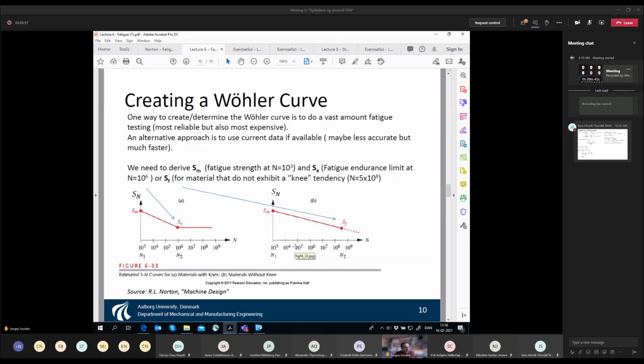They say that they follow this concept, and then their specimen failed when the accumulated damage was equal to 4. And then another group of researchers, doing other experiments with other specimens, found that the failure occurred when the damage was 0.15. So these are extreme cases. All right, thanks.